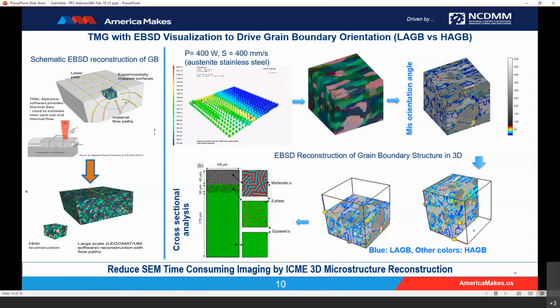Here, build analysis corresponded to a power setting of 400 watts and a speed of 400 millimeters per second. With this configuration, the TMG is used to calculate laser spot size and corresponding material flow paths in support of the melt pool throughout the heat-affected zone. The EBSD visualization software can generate three-dimensional images of this experimental process. Grain boundary misorientation angle from 0 to 62 degrees is shown in the upper right, and grain orientation cross-sectional analysis is depicted in the lower right.